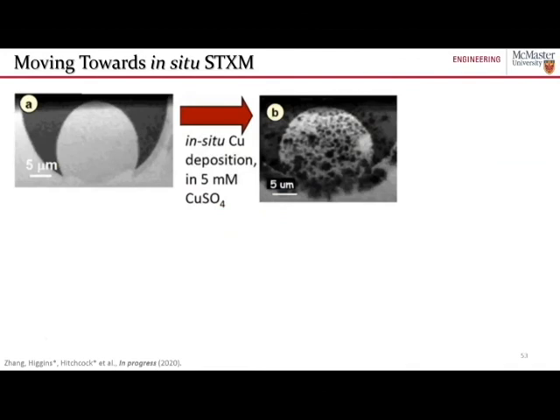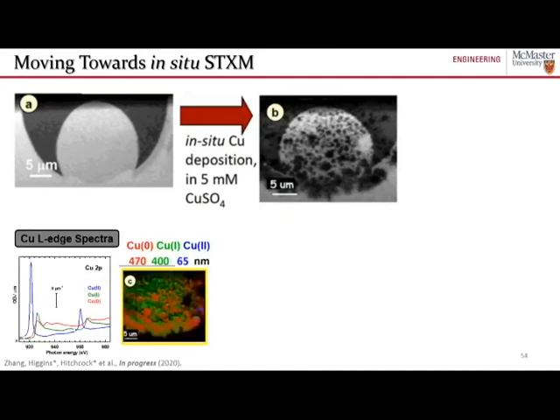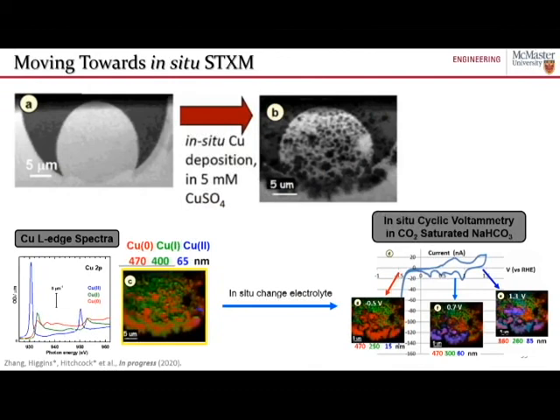Just some preliminary results on that front. What we did first is we took our working electrode and we electrochemically deposited copper, which is a very good electrochemical CO2 reduction catalyst, in a copper sulfate solution. Then we switched out the electrolyte to put in sodium bicarbonate that was purged with CO2, so our reactant purged electrolyte. And we did characterization of the copper electrode at varying electrochemical potentials. So we got a very nice cyclic voltammetry profile, and we're able to collect STXM images at different electrochemical potentials, setting the stage for doing some in situ characterization of catalyst materials under electrochemical CO2 reduction conditions.